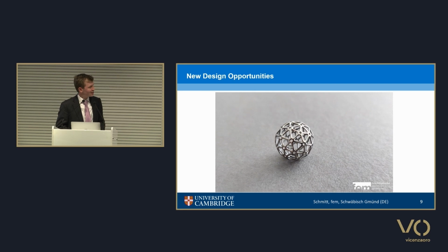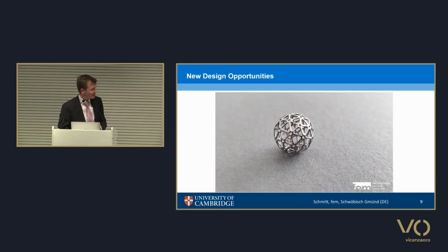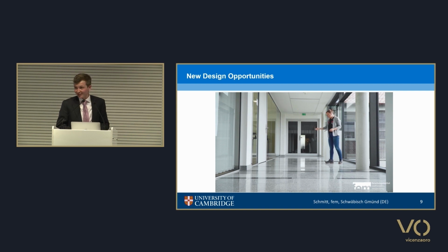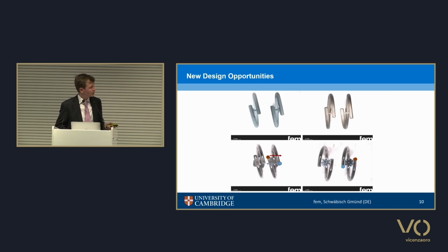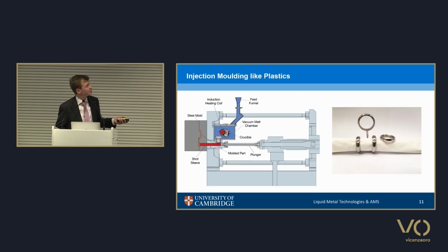So you've seen this video already, but it's worth demonstrating again because it's quite incredible, really. I thank Ulrich for letting me use it. And as you'll see, the elastic behavior is quite incredible, and it actually sounds a lot like a rubber ball simply because of that elastic phenomena. And so failure here will occur by the shear bands, but that occurs at much higher strains, allowing the ball to bounce as much as it does. And again, we get new design opportunities courtesy of these metallic glasses because of their high elastic properties and the fact that because they're so hard, the gems won't deform the metallic glass.